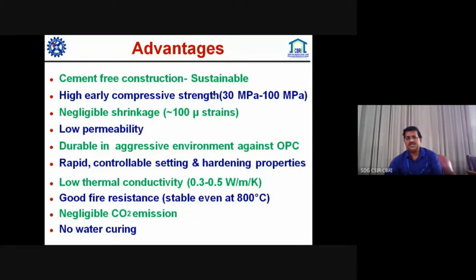It is cement free, and its strength is very high, going from 30 MPa to 100 MPa, and within 1 or 2 days we can have more than 20 MPa. Shrinkage is very minimal, with low permeability. It is very good against alkali and sulfate attack, in marine or coastal structures. It has low thermal conductivity and excellent fire resistance. Concrete starts deteriorating after 200 degrees centigrade, but this has been found to be very good even up to 800 degrees centigrade. And last but not least, we don't require any water curing, which is the biggest issue in cement based concrete or mortar, where we have to do water curing or moist curing continuously.